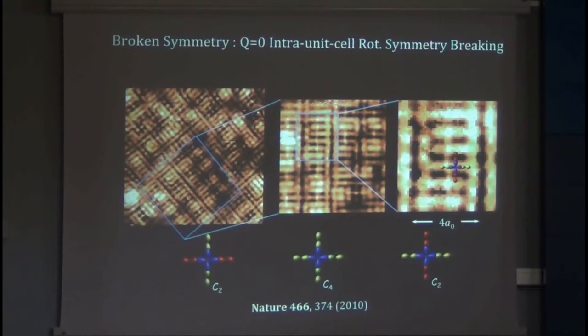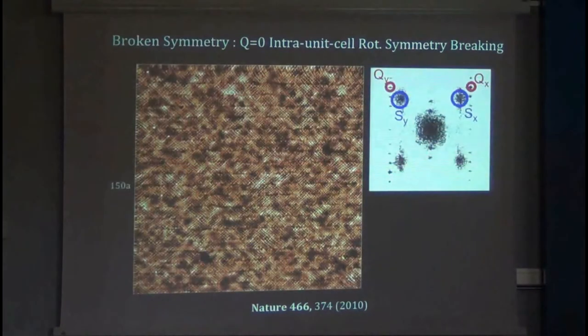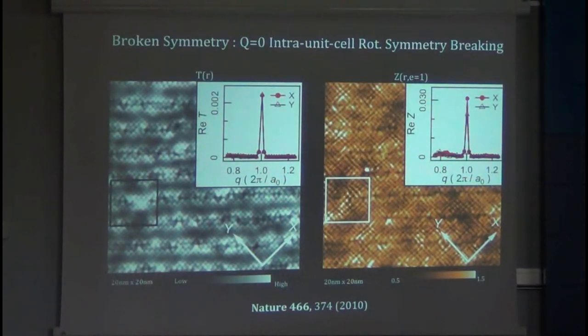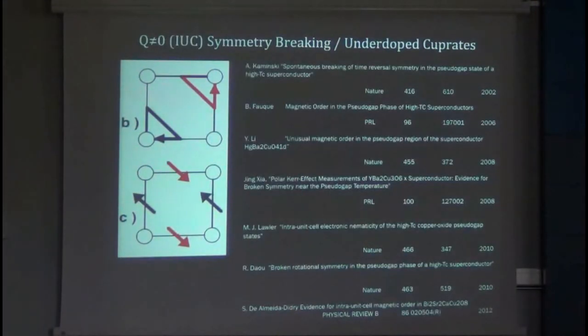So there's another broken symmetry here. It's a broken symmetry inside each CuO2 unit cell. We already knew this around 2007, but there's a quantitative way of measuring it, which we finally figured out. You take the Fourier transform, you look at the two Bragg peaks. They contain the information about what's inside the unit cell. Then you take the ratio of the intensity of one Bragg peak to the other, the ratio of the X Bragg peak to the Y Bragg peak. If those two peaks are not equal, then rotational symmetry is broken inside the unit cell, trivially. We found that that's globally true in the underdoped cuprates and reported it in 2010. And furthermore, there's a very wide range of evidence that there is a Q equals zero, that means it's periodic with the crystal unit cell, intra-unit-cell broken symmetry in the underdoped cuprates.